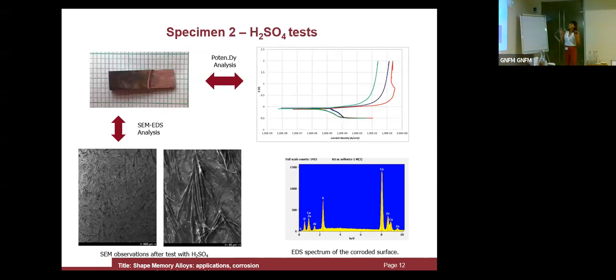Okay, this is the specimen after a sulfuric acid test. Here again, we have some observation of the martensite forms. Obviously, in this case, we have a product mainly of copper sulfate because we use sulfuric acid. And also again, the current density with respect to different concentrations, 0.01 molar, 0.1 molar, and 1 molar. And then again, the EDS spectrum of the corroded surface.